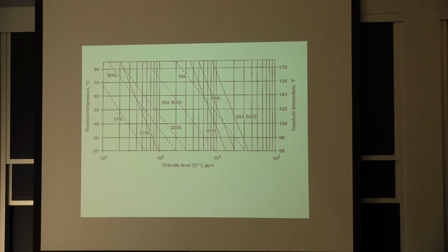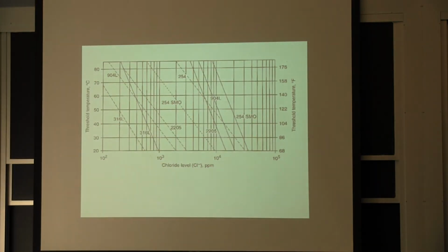This is probably the key concept, where different alloy chemistry in stainless steel will give you more or less resistance to pitting corrosion. And that's just about trying to initiate the anodic reaction; continuing in that area is dependent on how much chrome and how much nickel you have. It's unfortunate, but it's the truth that the more money you pay for your stainless steel, the more resistant it's going to be to that pitting corrosion. And I've used this graph a lot in terms of determining, okay, so I may have salt water. This is going to be my highest temperature. I want to make sure I'm not getting into this zone. So there are a lot of those available.